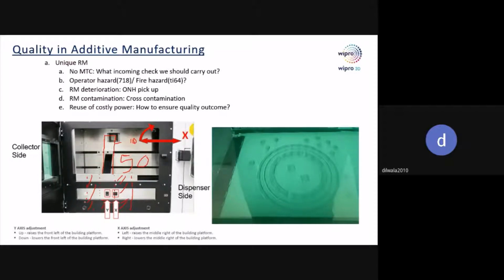So if you go through the build process, if we need like 10 kg of component, we are putting in some 50 kgs to cover the complete height. Now after the build is over, some 10 kgs of part is removed and some additional 10 kgs get wasted in the form of supports, wastage on the machine, and powder wastage during cleaning. So we will be left with some 20 kgs powder in the dispenser and some 10 kgs powder in the collector.